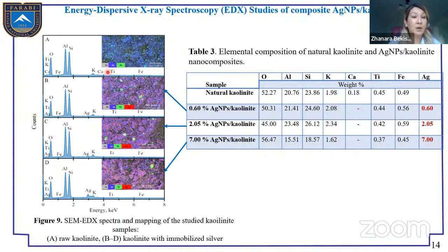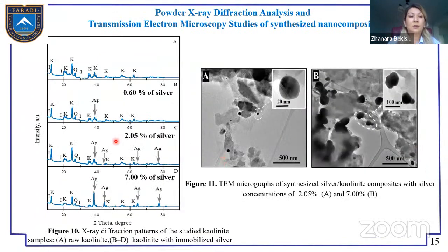We can see the EDX spectra and mapping of the distribution of the elements on the structure of the kaolinite with different concentrations of silver. The formation of silver was confirmed with X-ray diffraction, with peaks at 38, 44, 64, and 77 degrees 2 theta confirming the silver formation on the kaolinite. The size distribution was studied in the micrograph STEM, with a predominant size from 15 to 20 nanometers, and they also have some twinned crystallines of the silver.